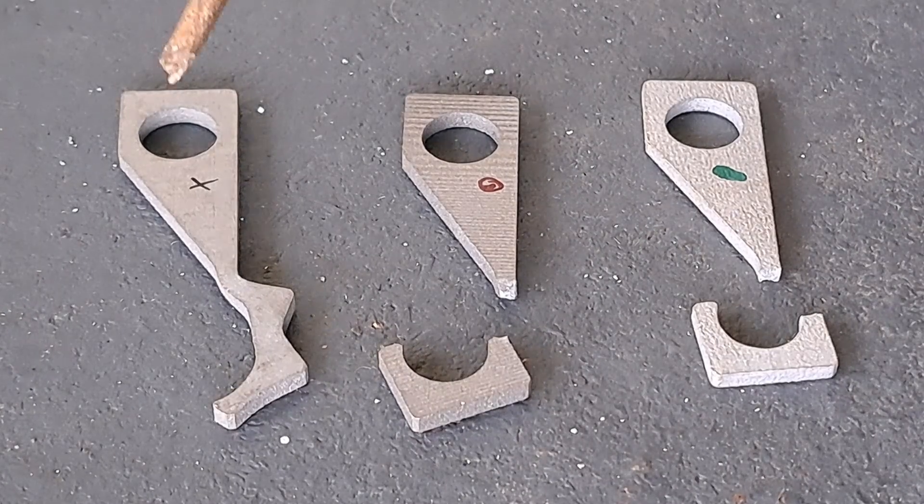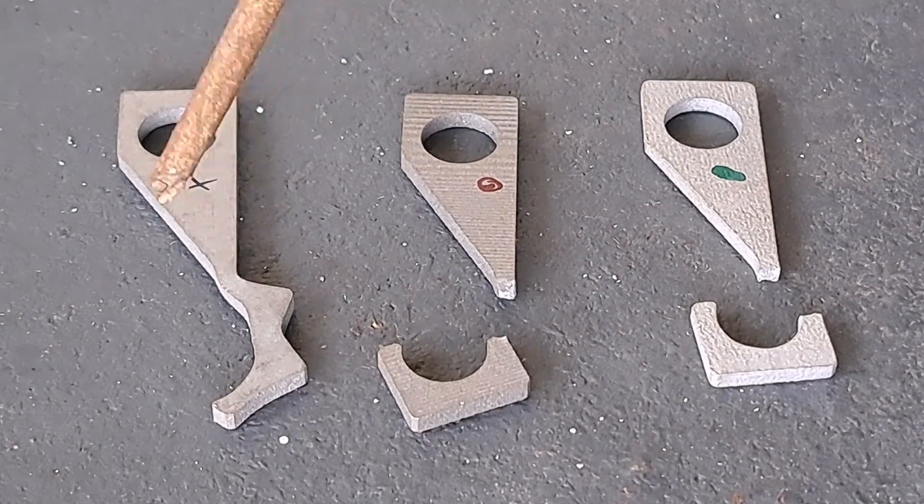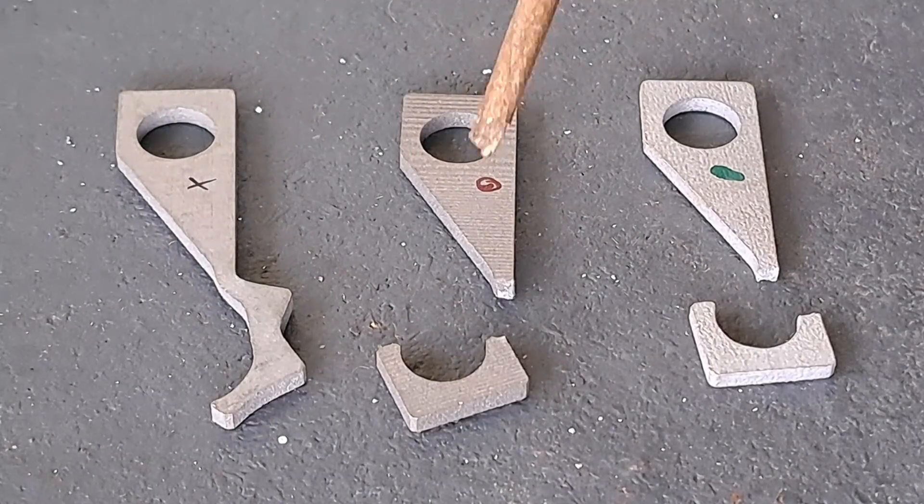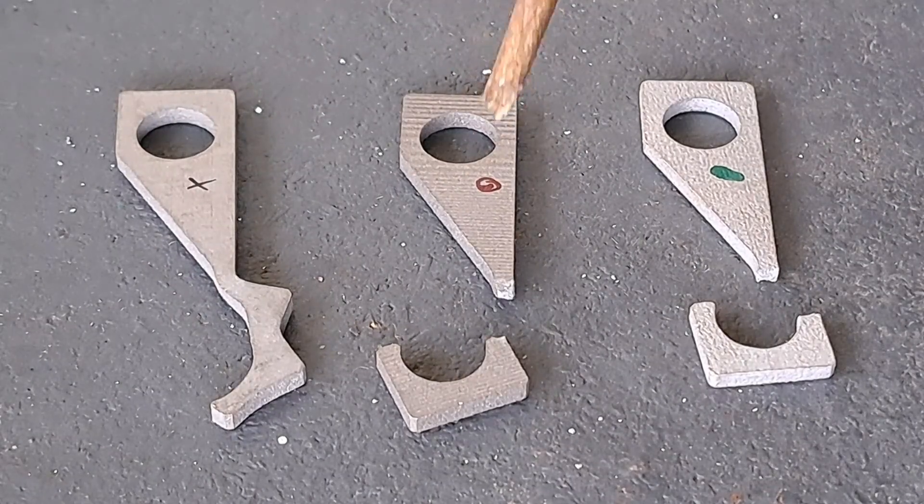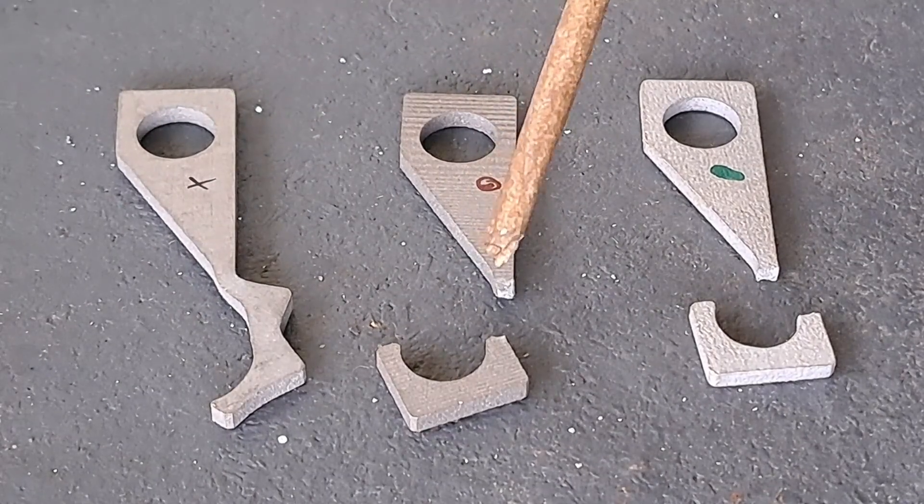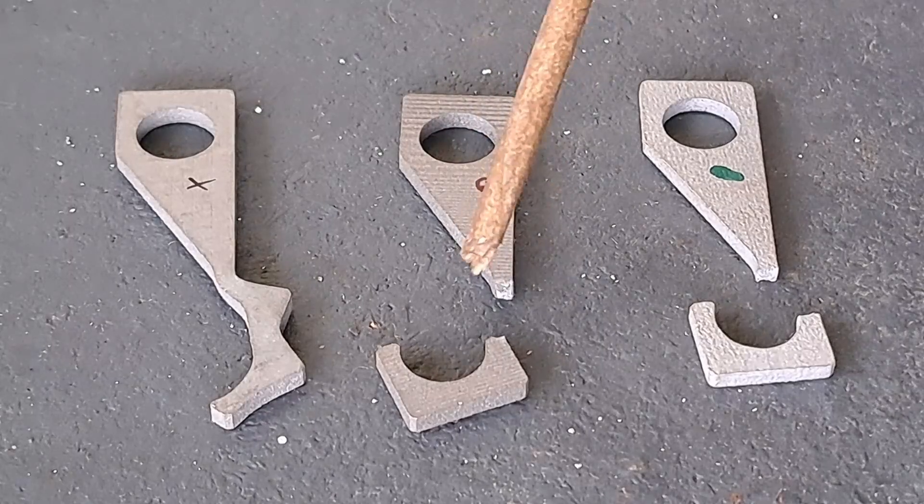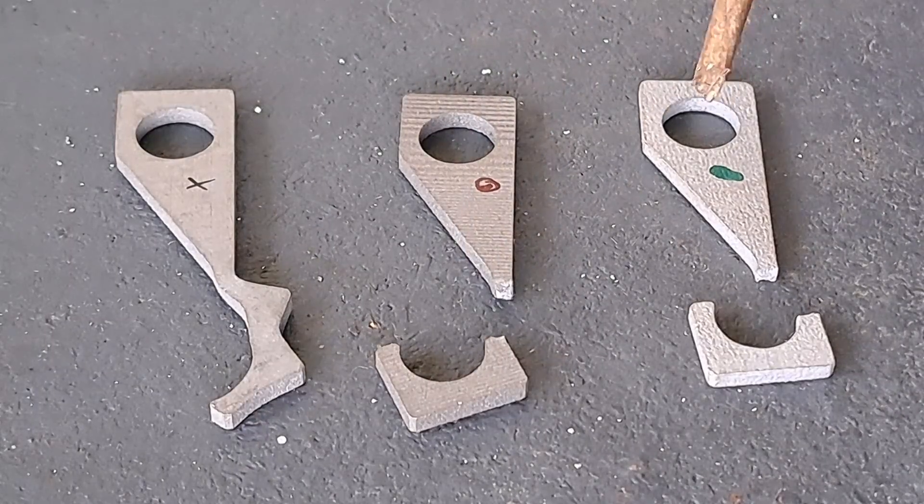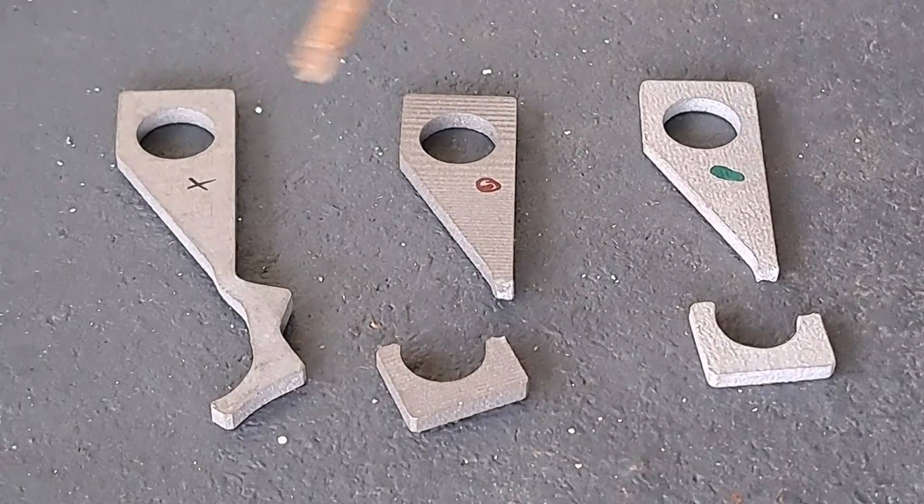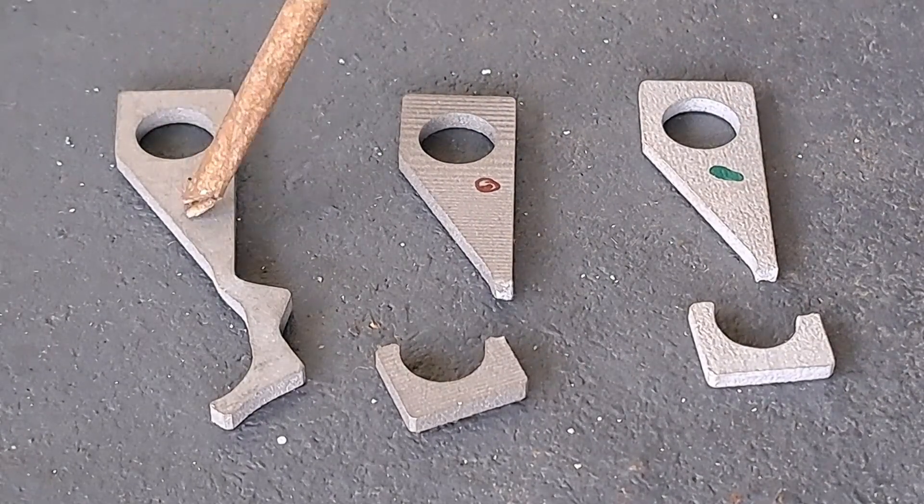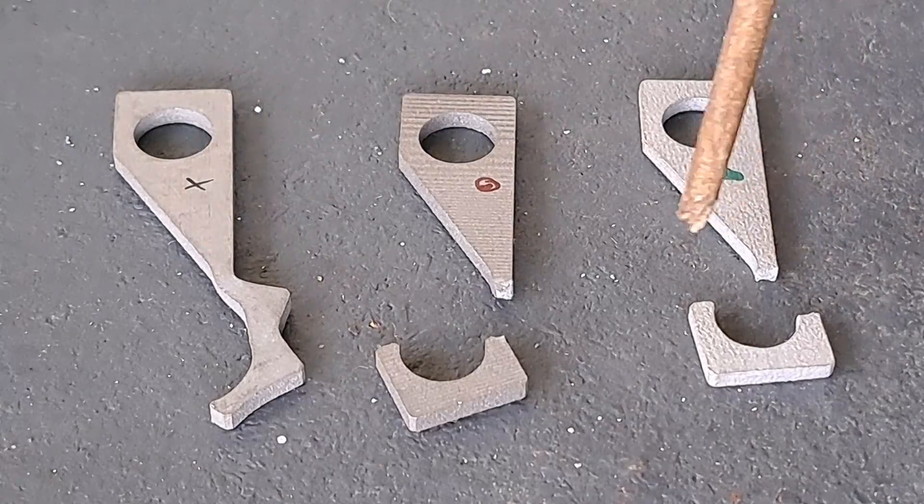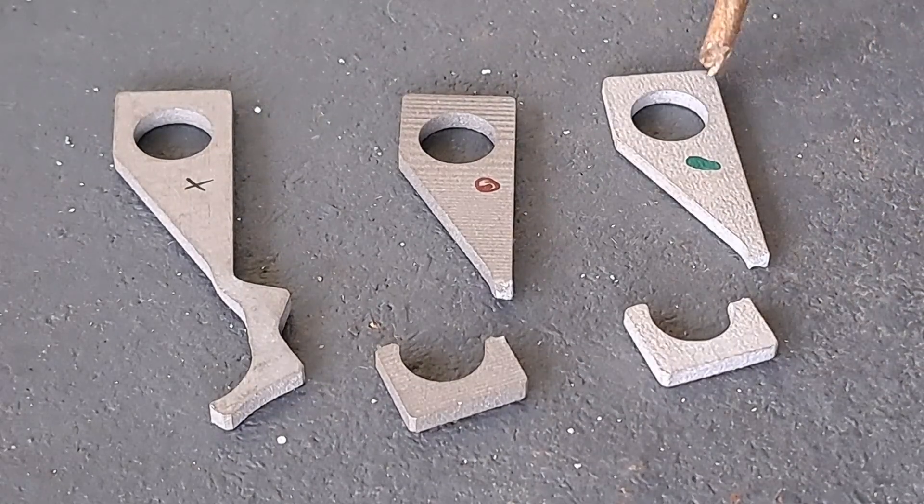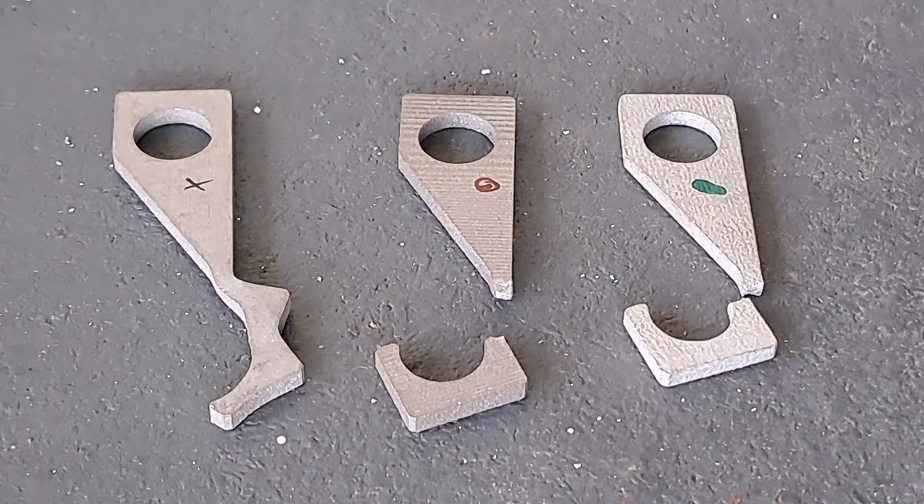And this is how they broke. Stainless steel is just deformed and slipped from the hook. Tool steel, it is a brittle material but of course it is harder and it just broke. And I thought the aluminum would have similar deformation like with the stainless steel, but it also broke on quite small load.